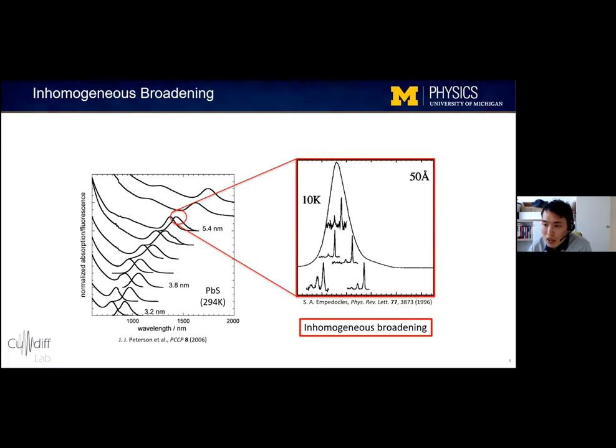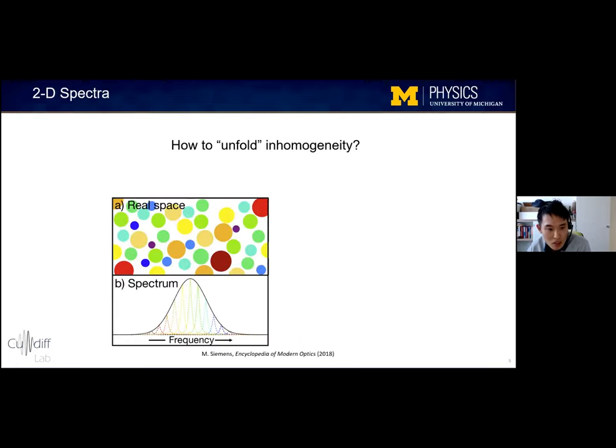So now you can understand the difficulties with studying the optical properties of nanocrystals, since the fluorescent spectrum of ensembles are these broad line shapes that only give you information about the nanocrystal size distribution, while the fluorescent spectrum of individual nanocrystals varies a lot even within the same batch. And if you want to design a device using these nanocrystals, you want to know about their ensemble average properties, since you don't want to design a device around the properties of a single exceptionally good or exceptionally bad nanocrystal. So here's the situation I described on the previous slide, where you have nanocrystals of different sizes, all emitting light at slightly different wavelengths. And we want to know about their ensemble average properties, but all of their individual spectra combine to give us this inhomogeneously broadened spectrum. So the question is, how do we unfold this inhomogeneous distribution to get at the underlying homogeneous line shapes?